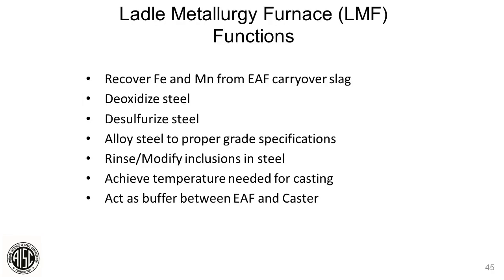So there's many functions that we have to do at the LMF, and part of it is we recover some of the Fe, iron, and manganese from the EAF carry over slag. So when we tap, some of the slag that's in the furnace goes to the ladle furnace. There's some oxidized iron and manganese in there. We can actually get a little bit of that out as a yield gain. Very small percentage, but it is there.